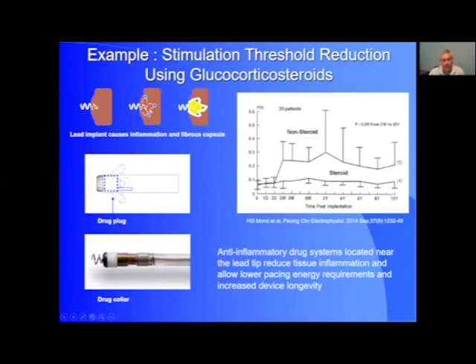muscle wall, and when that's implanted, there's a fibrous reaction that can form a capsule around that implant and can raise the resistance of the lead to provide effective stimulation. And so in the graph to the right, you can see some clinical data where the use of steroids reduced the threshold, the voltage required to provide effective pacing by several tenths of a volt, which is physiologically and more important for the life of the battery, very important, and will have an effect on the useful life of the battery. So basically there is a number of different steroid-eluting component designs. There's plugs that can be embedded inside the tip of the pacing lead and provide the drug release, or collars which go around the outside and provide a slow release of steroid.